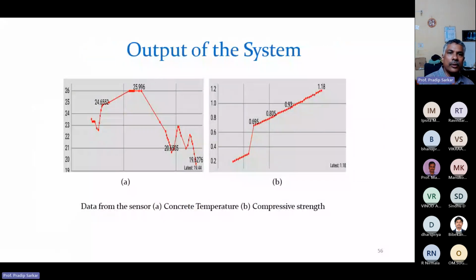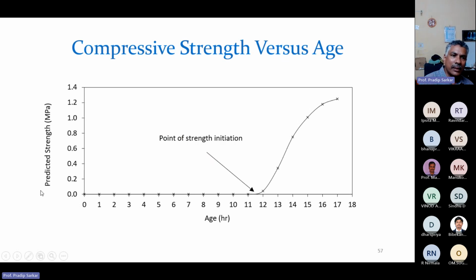Now you can see here the concrete temperature data is coming like that, and the compressive strength data is coming like that. This is the temperature time history, and this is the strength time history. The strength is progressively increasing from 0.69 megapascal to, for some typical data, 1.18 megapascal. If you see the strength versus age over a large time interval, the point of strength initiation is about 11 hours. After 11 hours, the concrete actually started increasing in strength.